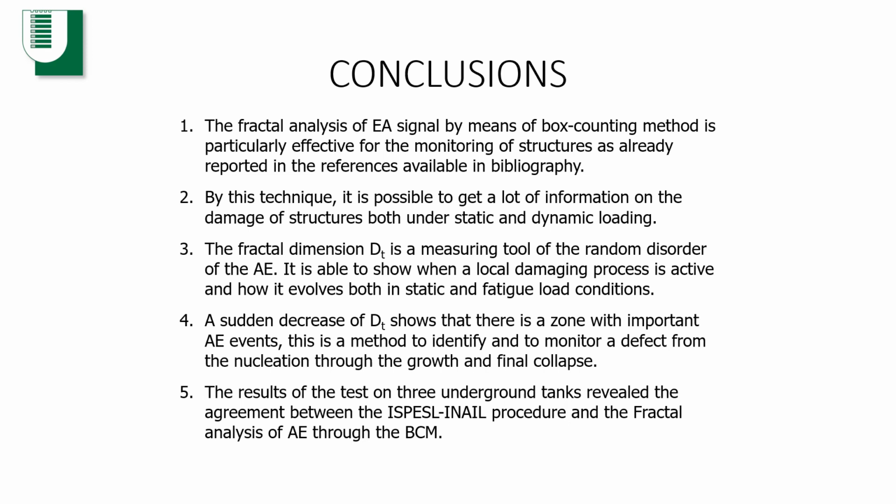Based on all that we exposed, it is possible to conclude that the fractal analysis of acoustic emission signals by means of the box counting method is particularly effective for monitoring structures, as already reported in the references available in the bibliography. By this technique, it is possible to get a lot of information on the damage of structures, both under static and dynamic load history. The fractal dimension is a measuring tool of the random disorder of the acoustic emission. It is able to show when a local damaging process is active and how it evolves.